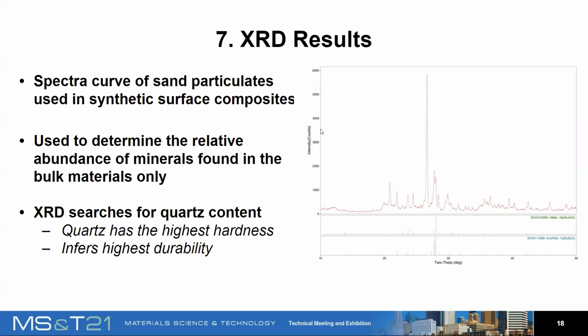So these are the XRD results. This is the kind of spectra you would get in an XRD test. You can see here the y-axis has intensity and the x-axis has 2 theta degrees. This is usually used only for the relative abundance of minerals, usually in bulk materials. The XRD tests can find a lot of minerals, but more specifically, we are interested in finding quartz. The reason we want to find the amount of quartz in our sample is because quartz has the highest hardness. And the highest hardness also infers the highest durability, meaning we can kind of tell how long our material can last in our synthetic material and how it degrades over time.